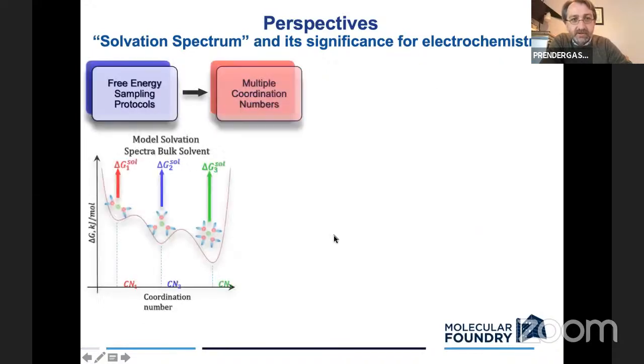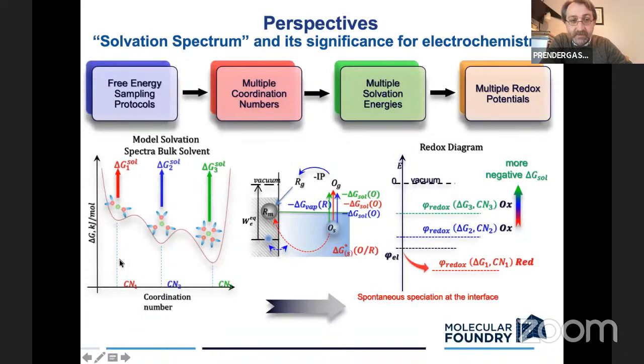However, if we now think about multiple coordination environments being stable and having their own populations, you realize that they have ordered free energies of solvation, which means they have ordered redox potentials. And so what could happen is that the least stable of these species, which you don't see a very high population of, might be the one that first gets reduced. And if there's enough time, depending on how fast you're scanning your voltage, that population will be replenished from the bulk. And so the active species might not even be visible in the bulk because it's such a small population, but it is the one that gets reduced first, and therefore your current is flowing through the production or reduction of that species. That's an interesting thing to think about.